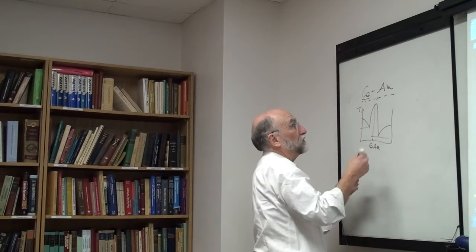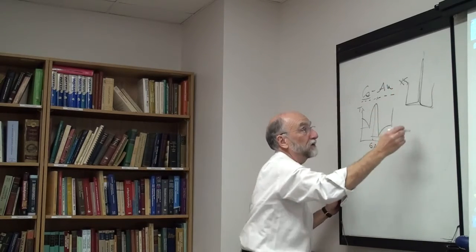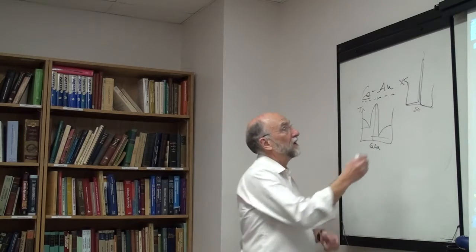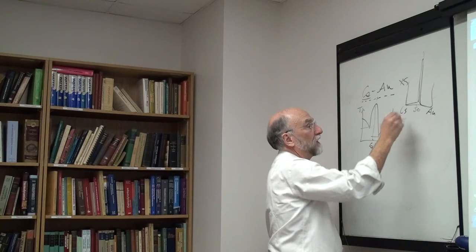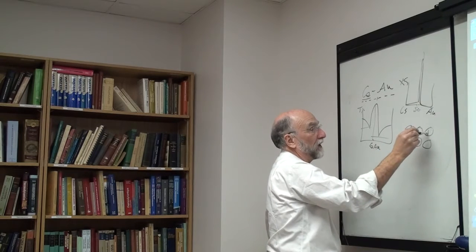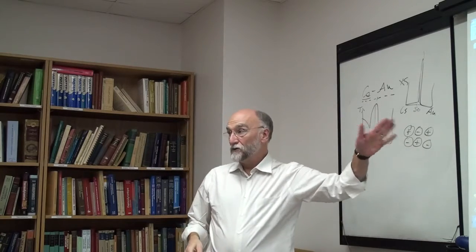And if across the liquid you were to plot the excess stability function, you would find it went boom like this, with a very strong peak at 50% cesium. So at 50% cesium gold, in the liquid state, you pretty well have cesium ions surrounded by gold ions, cesium ions surrounded by gold ions, like the cesium chloride structure. Okay, cesium gold, cesium gold, cesium gold.